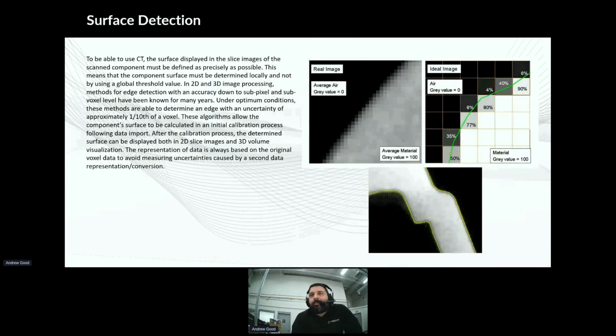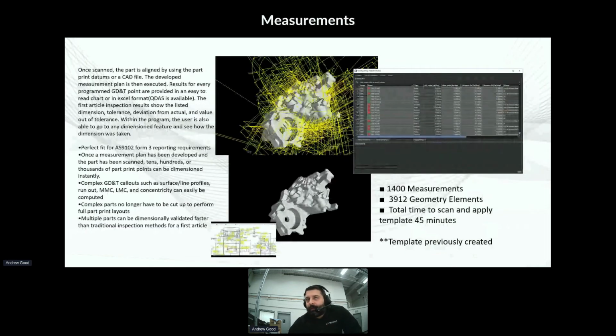But when we start getting into something a little bit more complicated with computed tomography, we need something called surface detection. It's great that you can see these voids or measure the wall thickness. However, if we're going to do anything more advanced, we basically need to surface it. So we use something called an isosurface or an advanced isosurface. It takes where it knows air is and material and creates a local adaptive line around the entire area. You have to remember this is in full three dimensions. This can actually be accurate to 1/10 of a voxel, so you can get very, very high precision, which then helps us to do measurements.